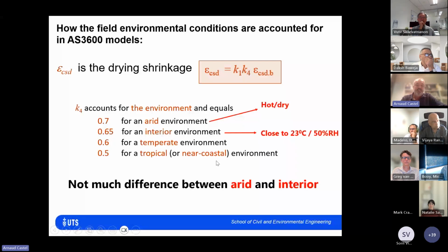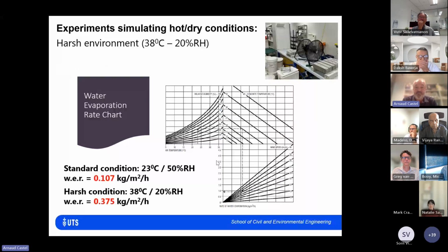Okay, so we did a simple test. We had the same specimens. Some of them were in standard condition, 23 degrees, 50% relative humidity. And another set of specimens were stored in a different room with a temperature of 38 degrees and only 20% relative humidity. So very different exposure conditions, let's say.